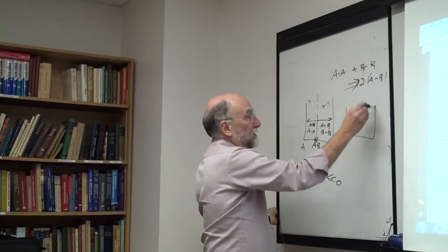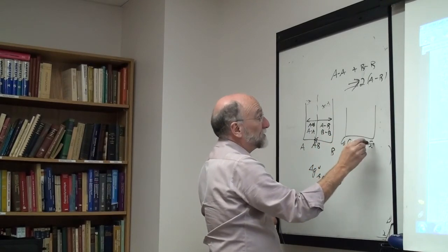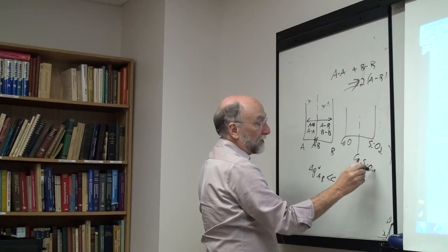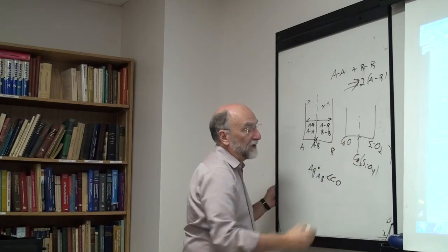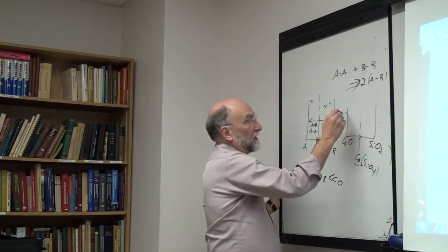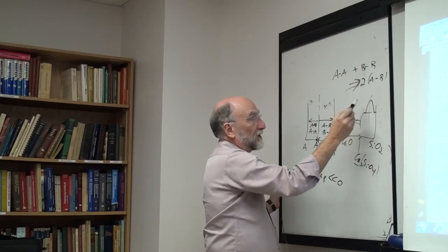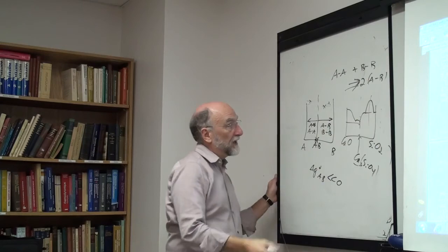A good example of this would be when you're doing your oxide systems, in calcium silica, for example. These are very strongly ordered around the Ca2SiO4 range. Here you've got your phase diagram on this side, and miscibility gaps on this side. Quite different chemistry on the two sides.